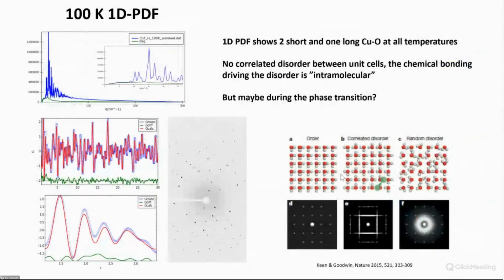But if you look at the PDF, then at any given time there will always be two short bonds and one long bond. So in the 1D PDF down here, you'll see two bonds that are 2 angstrom and one that's 2.3 angstrom. And this is 100 Kelvin synchrotron data from SPring-8. You can see that the diffuse scattering here is really minor. It's just going out from the center, but there's nothing really correlated in the diffuse scattering in this structure.